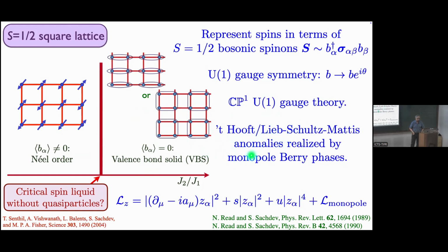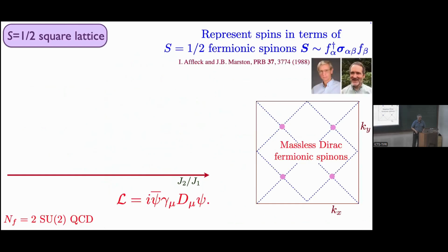But there were also monopoles to worry about because this U(1) gauge field is confining. And then various Berry phases of monopoles, which are related to Berry phases that Duncan computed for hedgehogs on this side. We computed them on this side and found the same Berry phases. And we showed that as a consequence of these Berry phases, there'd be a broken symmetry, there'd be a valence bond solid state. And this is now seen in numerous studies of the J1-J2 model, that there's a valence bond solid. But this appears at very low energies. And so now the question is, perhaps near the transition, there is a spin liquid. And in recent years, there's been a lot of evidence emerging that there is indeed a critical spin liquid here.